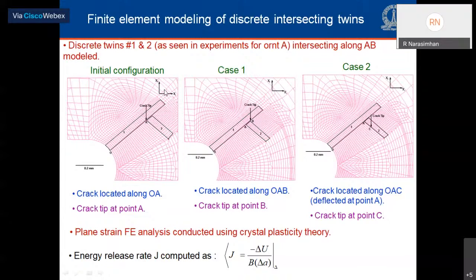If you look at the left side mesh, this pertains to the initial configuration where from the notch root, the crack is extended along OA with a tip located at point A. In the case 1 simulation, we assume the crack to extend along the twin boundary, the boundary of twin 1, without any deflection, with a crack tip located at point B. Whereas in case 2 simulations, we take the crack to have deflected at point A and to have extended along AC with the tip located at point C. The analyses conducted here are plane strain finite element analyses using the same crystal plasticity theory which I described. The energy release rate is computed as the rate of decrease of the strain energy with respect to crack area.